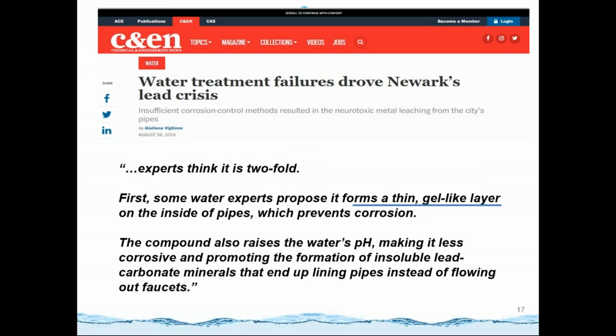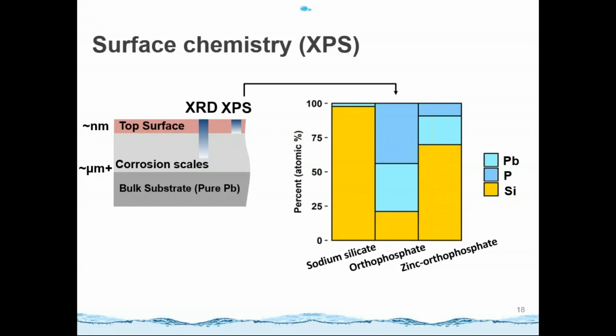So let's come back to the mechanism, because the first hypothesis is that the sodium silicate may form a thin gel-like coating layer on the surface of the lead pipe, because it may be very thin. So the technology we usually use in corrosion analysis may not perfectly match for analyzing the coating. So we use another tool called XPS. The figure on the left shows the XRD detection limit. It can usually detect up to around micrometers depth.